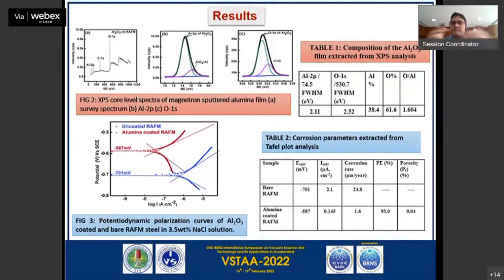Then after that, to characterize the corrosion properties, we have tested the coating in 3.5% NaCl. From the potentiodynamic polarization curve, you can see that the coated substrate has a higher corrosion potential of -587 millivolt as compared to the uncoated substrate. And we have calculated the corrosion potential, corrosion current density, corrosion protective efficiency, and the porosity of the coating.